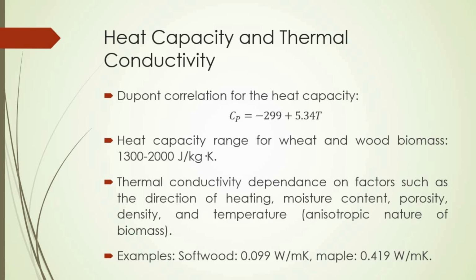For various wheat and wood biomass samples, the heat capacity ranges from 1,300 to 2,000 joules per kilogram Kelvin within a temperature range of 40 to 80 degrees Celsius. For biochar derived from the same materials and treated at 500 degrees Celsius, the heat capacity is narrower, ranging between 1,127 and 1,193 joules per kilogram Kelvin.